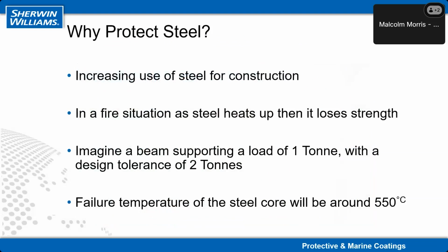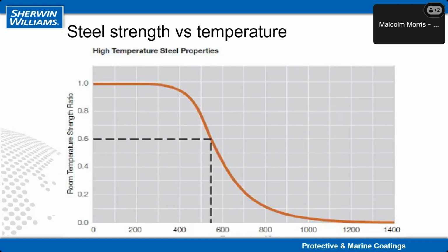But why do we need to protect steel? Well, in a fire situation, steel heats up, it loses strength, and very quickly, above about 375 degrees centigrade. Typically, an average steel beam will lose about half its structural strength above 500 degrees C. So anywhere between 400 and 600 degrees C, there's a rapid decrease in the load bearing capacity of structural steel, and above critical strength, obviously you're in danger of the building collapsing. So that's what we're aiming to do with reactive fire protection steel coatings, is to mitigate the effects of that fire and preserve the structure for as long as possible.